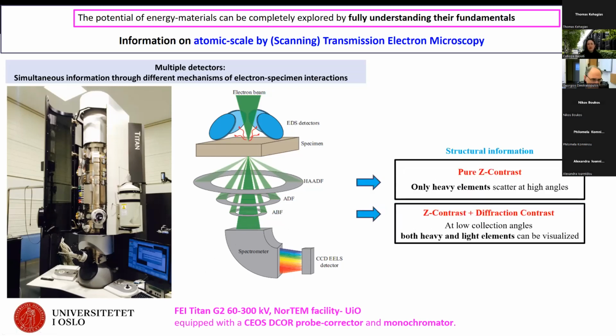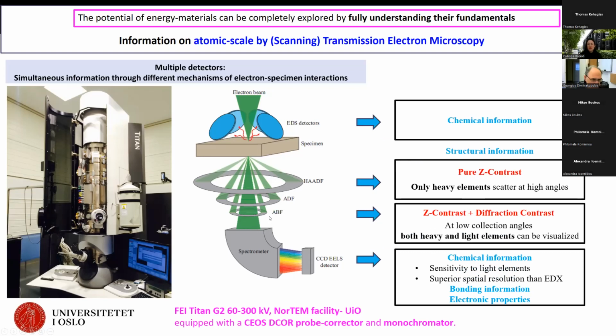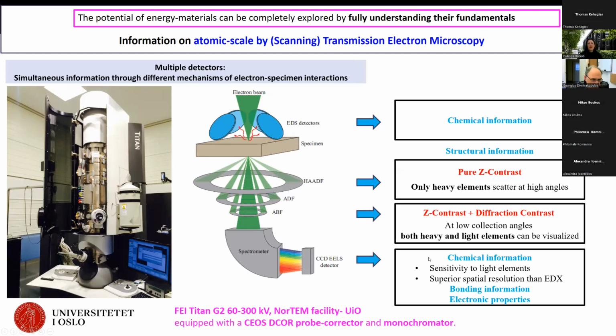For example, if we collect electrons that are scattered at high angles, we can have pure Z contrast images. Then we can start introducing diffraction contrast, and with annular bright field at very low collection angles, we can visualize both heavy and light elements. Along with the structural information, we can also have chemical information by combining spectroscopies such as EDX and Electron Energy Loss Spectroscopy.